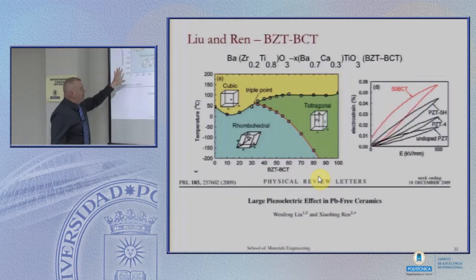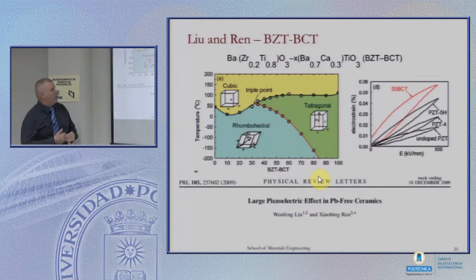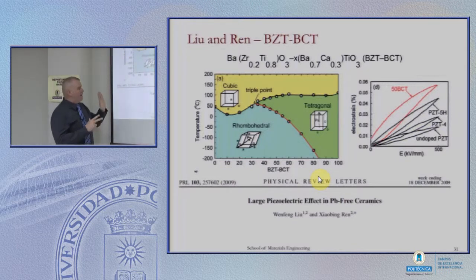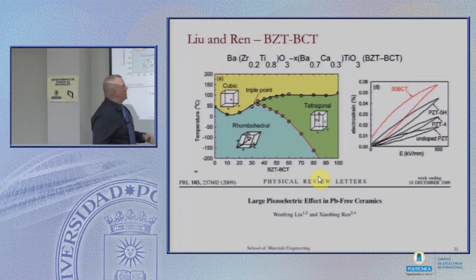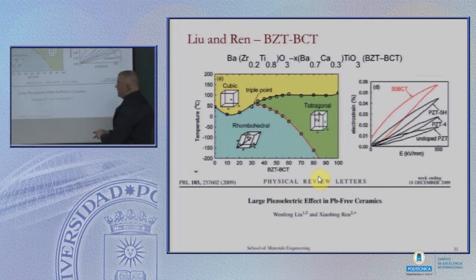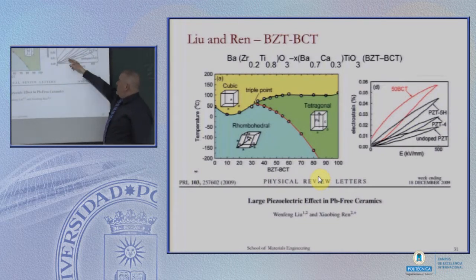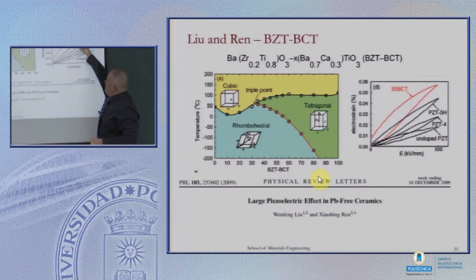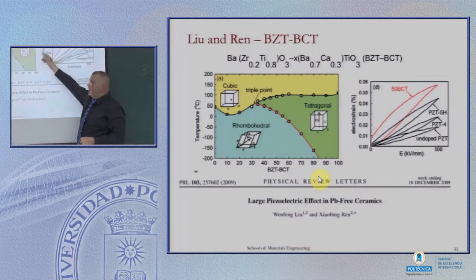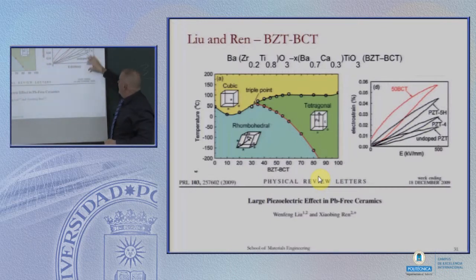So if we look at the material that Xiaobing Ren originally produced, and we compare it at room temperature under well-controlled conditions, the material is exactly at 50-50 at room temperature. It's pretty amazingly fortuitous that the best properties are exactly at 50% of this material and at room temperature. That's entirely a serendipity or an accident. But this is the 50BCT. This is strain applied to the material versus electric field. And these are some of the best performing lead-containing materials, right?